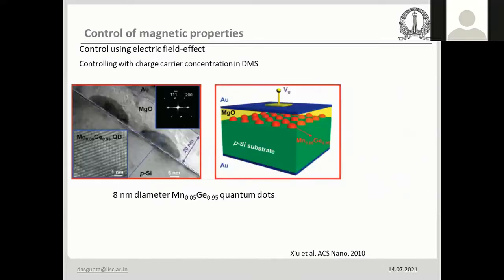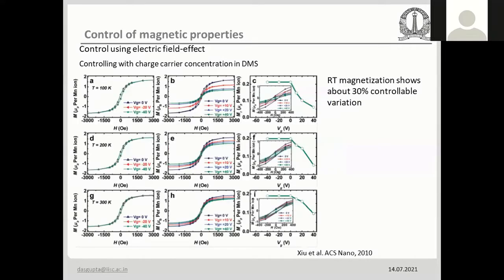Next comes this magnetic semiconductor. So these are called DMS, dilute magnetic semiconductor. In this case, it's 8 nanometer diameter quantum dots of manganese germanium, and you can see the manganese is much less than germanium. And these are dilute magnetic semiconductor. There was once upon a time a lot of work in this domain. Here also people could show some tuning. In this case, you can see that by application of certain electric field, you can change the magnetic hysteresis.